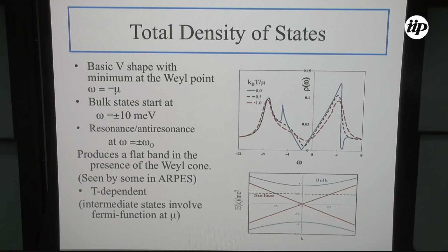But there's also another group of experiments on the same samples, taken on the same machine in Berlin, I think, with 1 milli-electron volt resolution, 1 degree angle, or something like that, which all show the same feature with some very narrow band close to the Fermi surface.